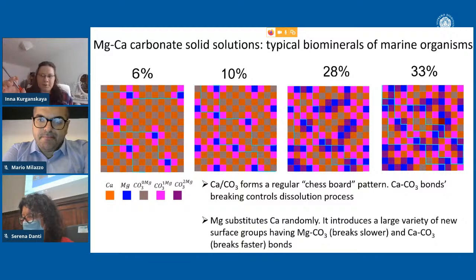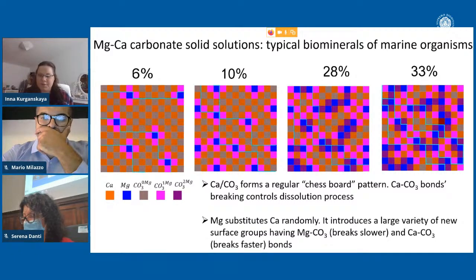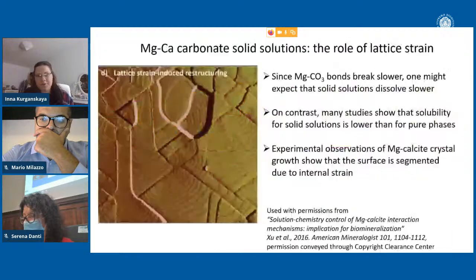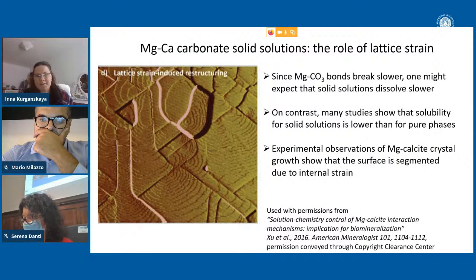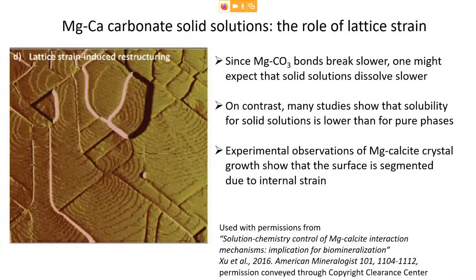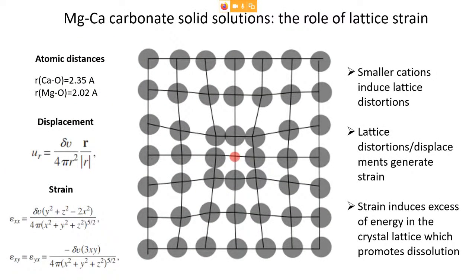And the first idea about the dissolution behavior of solid solutions is pretty much about the different rates of breaking for these bonds, but there is another important control which people became aware of. Since these cations have a smaller size, they introduce lots of strain into the lattice. Experimental observations of growth of this kind of material showed that it cannot grow smoothly. It forms segments, and the arrangement and formation of these segments is controlled by the internal lattice strain. And related experimental observations showed that dissolution of these solid solutions is faster and solubility is lower than pure phases. So why is it?